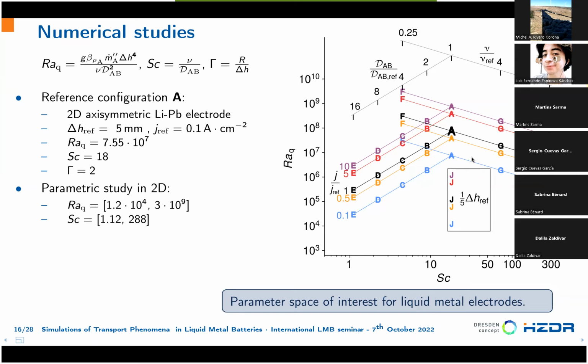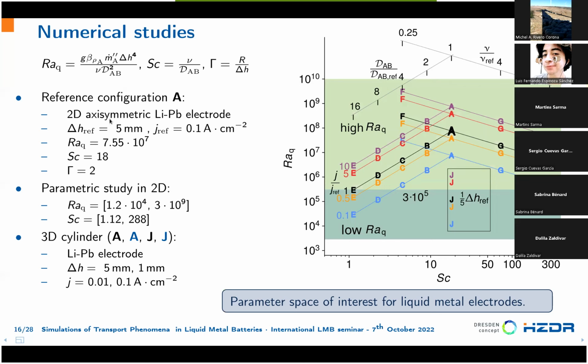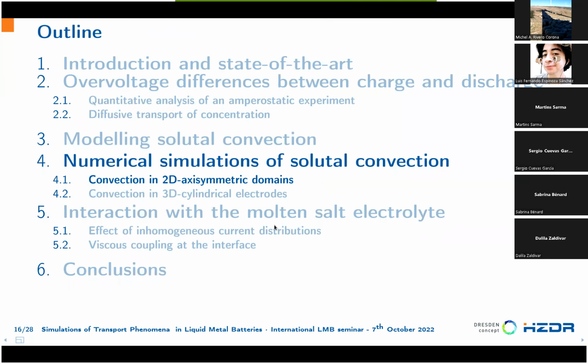We first studied this in 2D, with axisymmetric simulation, and then we move to 3D simulation, and we study this black and the blue configuration, so at 2 different current densities. This is to confirm that our 2D axisymmetric simulations are capturing the phenomena sufficiently well to study how solutal convection evolves in 3D. And we will analyze these 2 conditions later.